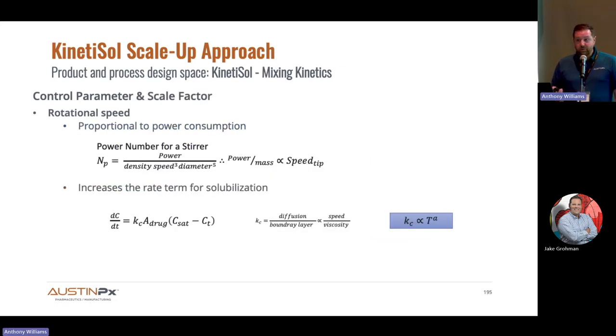The other parameter that is important is the speed. This speed is inherently like an RPM, right? There's a time factor here, and I learned at DPT a long time ago that we scale up stirrers in a very predictable way. It's not a perfect relationship, but in the end, the tip speed of the machine is relevant. But if you think about what I presented at the very beginning, the first thing we're doing is developing the formulation on a formulator, and then we transition that directly into formulation validation, get into the human PK study and make sure the formulation's behaving the way we want it to behave.